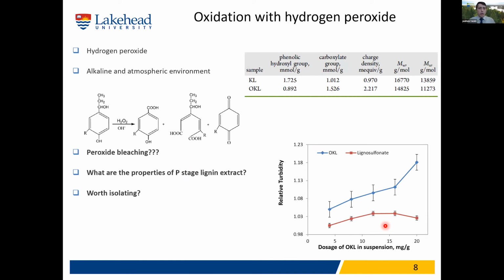So we moved on. So we studied hydrogen peroxide, and for hydrogen peroxide, again, we wanted to see if we could produce dispersant, and we did. And if you can see, again, the experiment was easy. We had lignin, and all of the lignin I have was either from LignoForce or LignoBoost. So they are pure lignin.